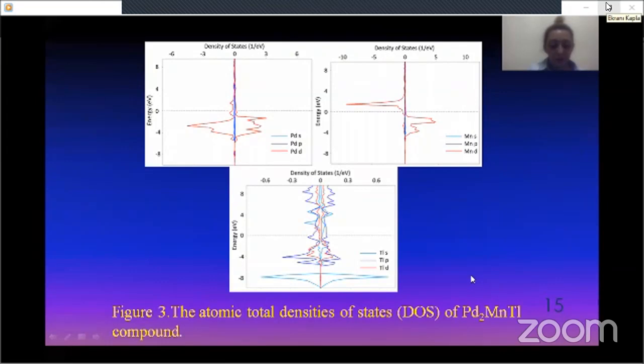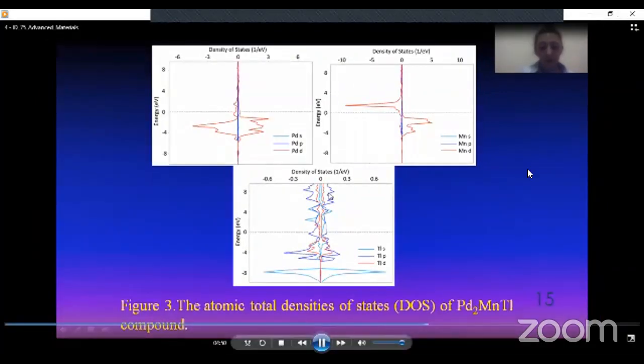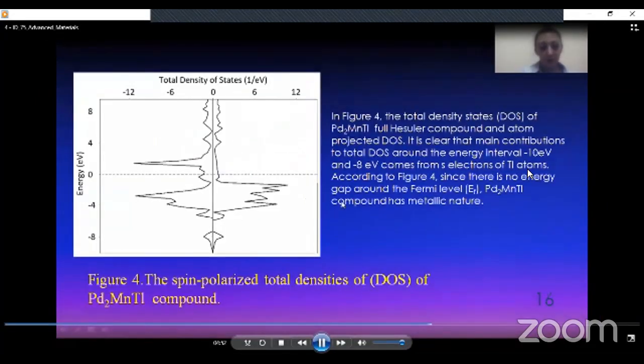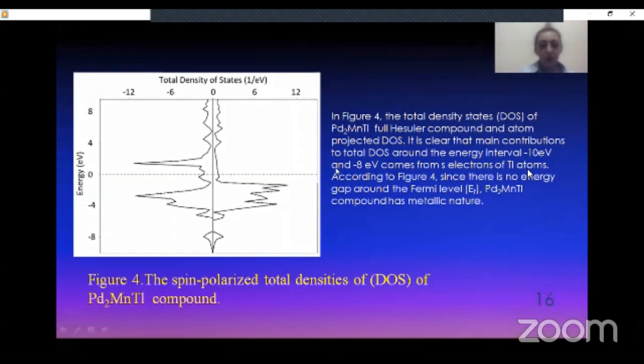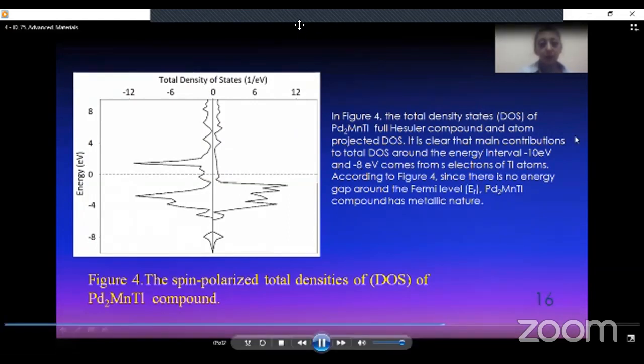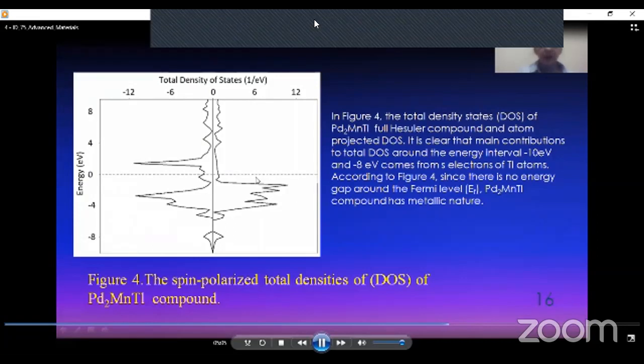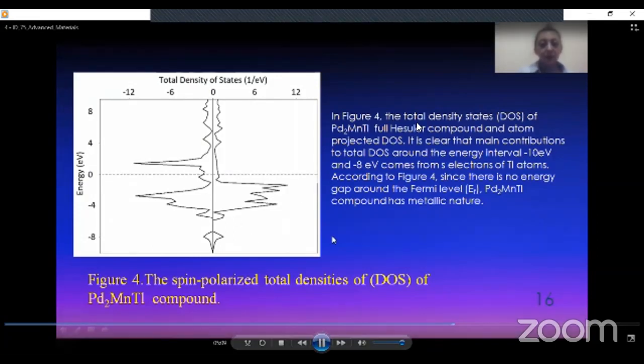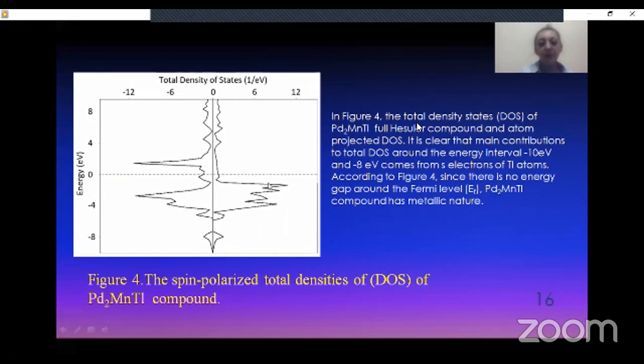Figure 3 shows the atomic total density of states of these compounds. In Figure 4, the total density of states of the palladium two manganese thallium full Heusler compound and the atom projected DOS are shown. According to Figure 4, there is no energy gap around the Fermi level. The palladium two manganese thallium compound has a metallic nature.